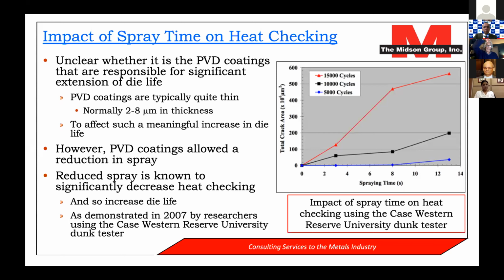takes a steel sample and dunks it in a bath of molten aluminum for about 10 seconds, pulls it out, lets it cool, and then it's sprayed, and then it dunks again, and it goes through this cycle. It's similar to a die casting cycle. And after 5,000 dunks and 10,000 dunks and 15,000 dunks, they take the sample out and look at the heat checking and characterize the heat checking in this way. And this is a laboratory technique that has been used in America for about 60 years and has really helped us develop information on die steels and heat treatment and process conditions on heat checking.